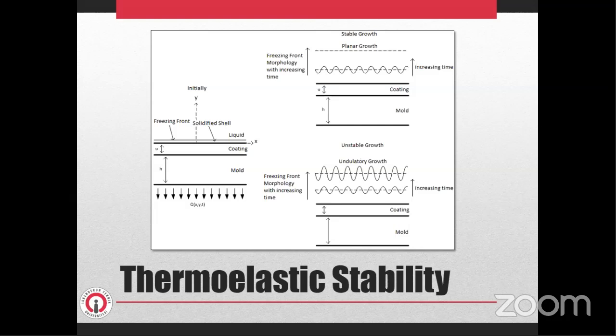The liquid material solidifies faster in the region where the heat flux increases, contrary to the region where the heat flux decreases. This behavior leads to an undulatory structure at the moving interface between the liquid and solid phases of the solidified material. At a very early stage of the process, the conditions at the freezing front are not affected by the conditions at the shell coating and coating mold interfaces. After a time period, they start to affect each other and undulations occur at the freezing front.